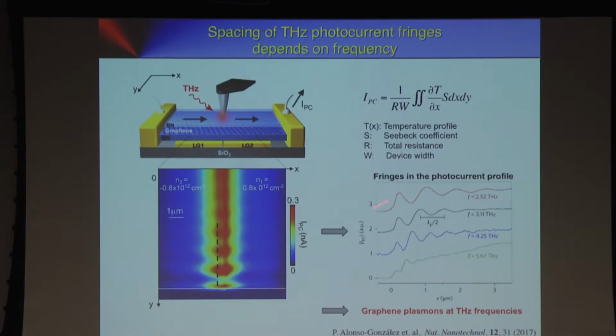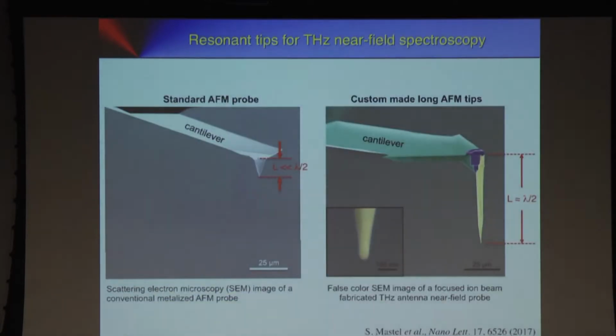So these are indeed plasmons. We can see here if we change the frequency, these wavelengths, the peak-to-peak distance, changes, and we have wavelengths of 1 to 2 micrometer. Also the photon wavelength is more than 100 micrometer. So it shows we have these exotic waves not only in the infrared, but we also have them in the terahertz spectral range. Well, then another thing to do is to optimize tips.